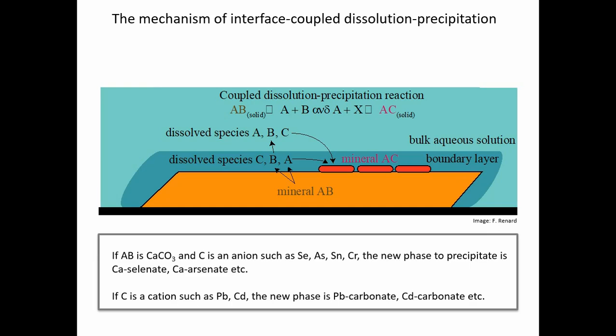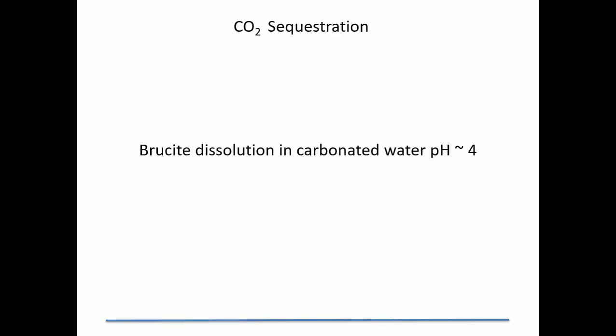cationic species. So dependent on the fluid composition right at the interface, but also right at the interface, as we saw from the dissolution, we have a very inhomogeneous, a heterogeneous surface. So we are able to supersaturate in specific positions on that surface.